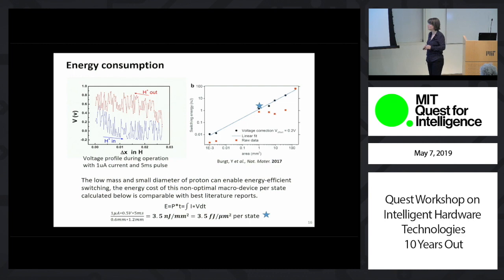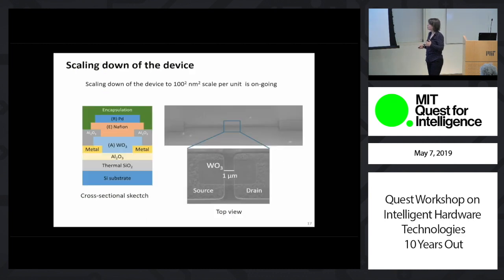We are very excited about this because, as I said, we're really working with a bulky device that gives this really low energy consumption, and we are in the process of scaling down our devices to channel lengths on the order of 1 micron currently, and we want to go lower than that, as well as thinner electrolyte and thinner active oxide layers. So we're in the process of making these devices more attractive, and we are excited about the current results that we got from them.